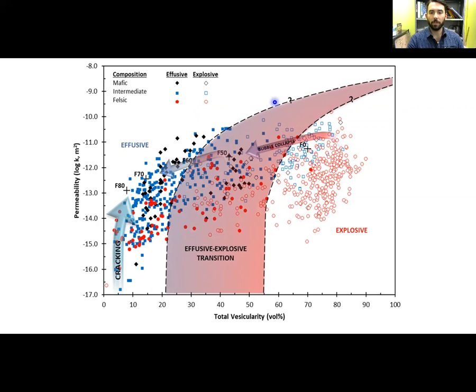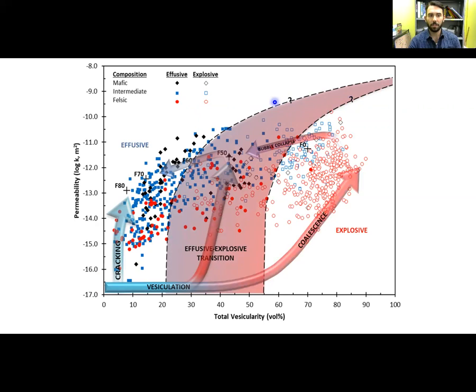Samples with high permeability and porosity can still erupt explosively because they fail to reach the very high permeability threshold for bubble-dominated systems. Our findings imply that this transition zone can be modulated by minor changes in crystallinity due to competing viscous and brittle behavior as magmas traverse this zone until it reaches a critical permeability. An intermediate crystal fraction, about 0.5, characterizes those magmas most likely to alternate eruptive behavior.